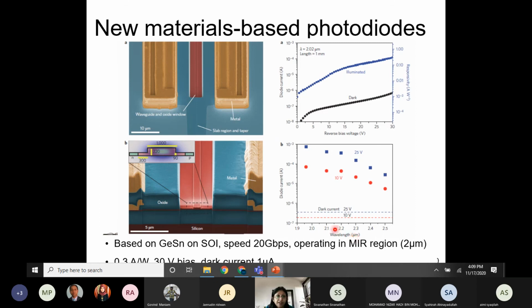Plasmonic photodetectors. So this is a high-speed photodetector using a germanium core, right? The active region is germanium core, and it has a cladding of gold on a silicon optical waveguide. All right, so the internal quantum efficiency is 36%, and the photodetection is up to 100 gigahertz. So it's for very high frequency optical communication application, right?